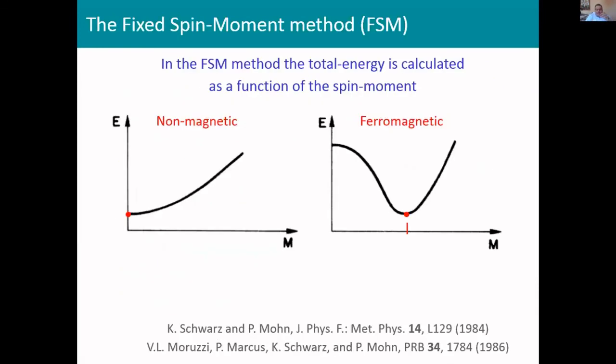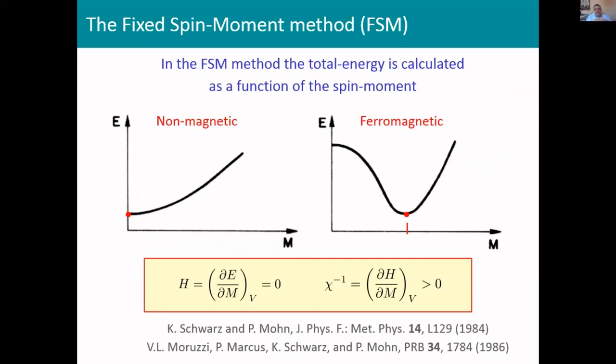Another important thing I want to mention is that in our calculation, we perform the magnetic properties calculations using the fixed spin moment method, not the standard spin polarized method, in order to see the behavior of the energy as a function of the magnetic moment, because this kind of plot contains very important information about the nature of the magnetism in the system.